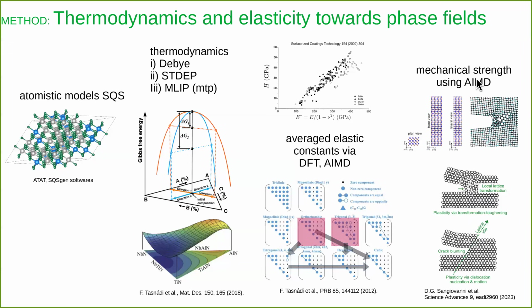And then we also implement ab initio MD calculations, where we are using big supercells of the alloys, and then we do some tensile or shear type of deformation to check the strength of the material. We do that using such tetragonal type of supercells. But we also implemented and use some notch models to see plasticity and also dislocation formation, and so forth. So these are the methods that we are using.